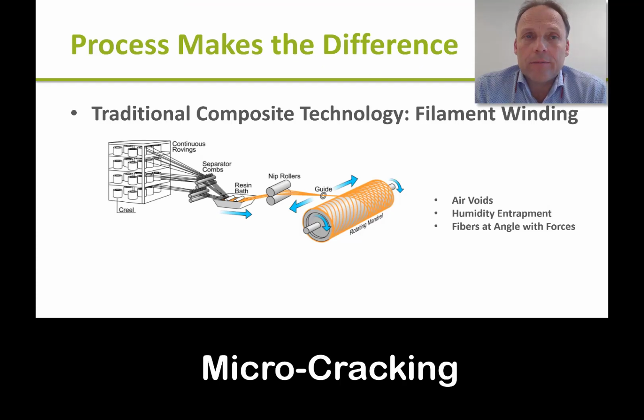So how is that done? Well, the process makes the whole difference. Just about every composite tubular is made by the process of filament winding, which is shown in the diagram below. The fiber runs through a resin bath to get fully wetted, and is then wound around the mandrel very much like cotton on a reel, up and down until you get sufficient glass to give the pipe its strength. Inevitably though, in that winding process, there is going to be an entrapment of air and an entrapment of moisture, because moisture from the air likes to sit on the glass. So that moisture and the air are trapped as small bubbles in the composite structure.